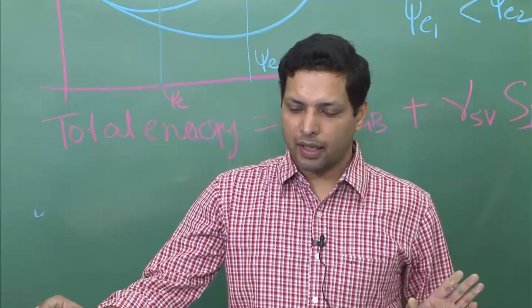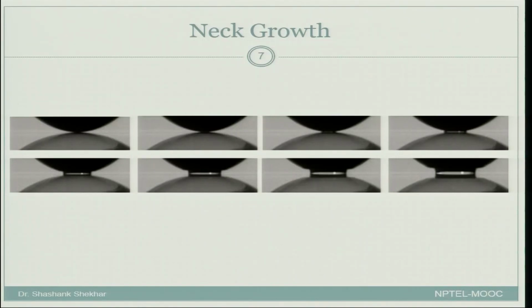We have always been saying that in the neck region, just a small amount of addition of the mass will change the surface area by a large margin. Let us look at these two particles. These are in the liquid state. Now, when these two particles come together, you see a very small neck has formed. So, the amount of material that has gone over here is very small, but how much has the surface area reduced? Now, the overall surface area would initially have included the whole curvature, but now just a small amount of addition has reduced the surface area in both the spheres up to this length x.